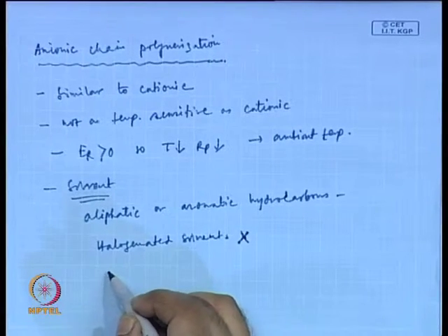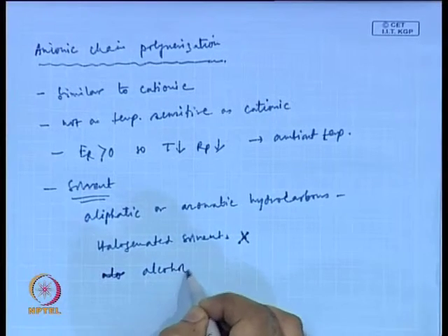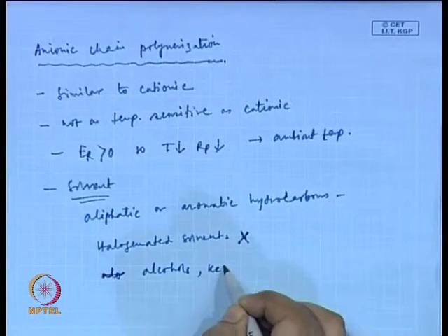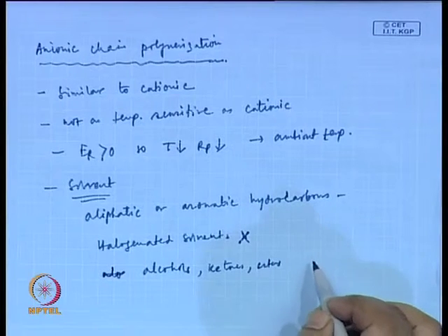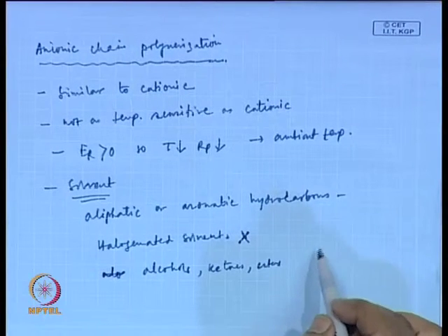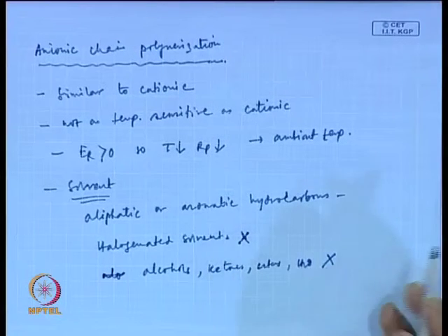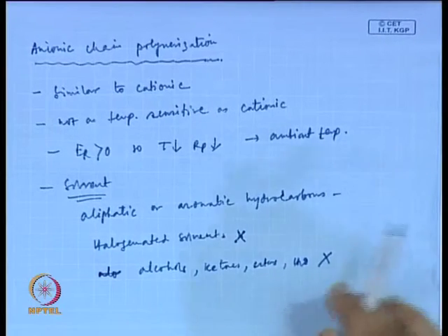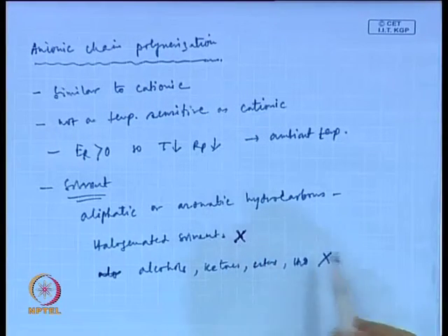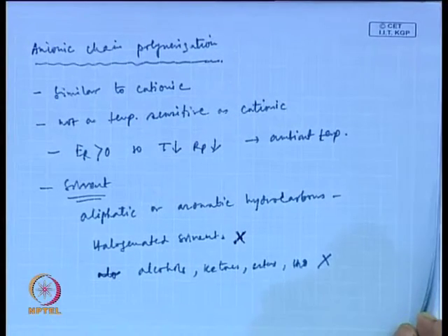Other polar solvents like alcohols, ketones, esters also cannot be used, as well as H2O, for the same reason, because they can very quickly react with the carbanionic propagating species and terminate the chain reaction.